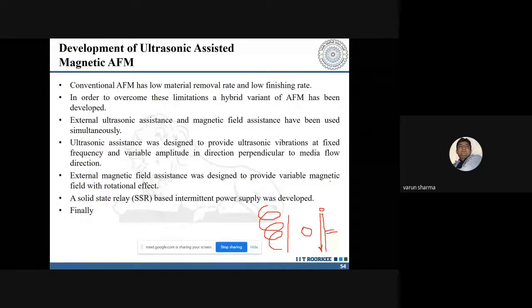Fine. Now what is the case? It is traveling linear, but it is traveling along the boundary, so it will be having a sinusoidal motion towards this particular end. So there will be a sinusoidal trajectory of that particular abrasive particle. Now, when we were developing ultrasonic, I was having sinusoidal motion of the abrasive particle. If I'm developing a centrifugal assistance, I am going to have a spiral trajectory. Now what we did is we tried to develop a combination of it. We tried to hybridize this particular process and we categorize that particular thing as an ultrasonic assisted magnetic AFM. So we got a patent of this particular process. So what we did over here is we tried to superimpose the ultrasonic vibrations with the magnetic assistance over here.